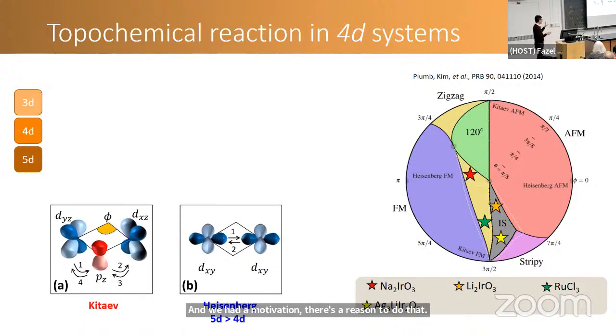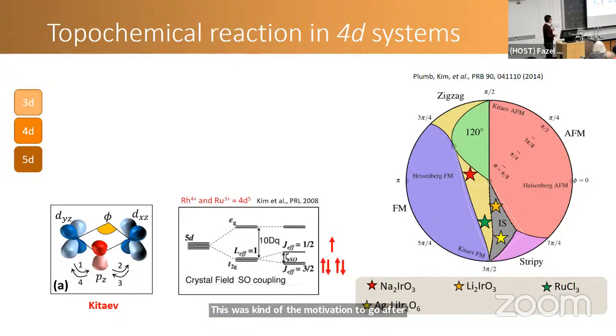And very simply put, that reason goes as follows. When you go from 5d to 4d, the spatial extension of d orbitals shrinks. 5d orbitals are bigger, 4d orbitals are smaller. And therefore, both this indirect Kitaev interaction and the direct Heisenberg interaction, both of them become weaker. But it so happens, if I understand correctly, that the Heisenberg interactions decay faster than the Kitaev interaction, which means that this ratio of Kitaev to Heisenberg coupling seems to be higher, in fact, in a 4d transition metal than in a 5d transition metal. This was kind of the motivation to go after 4d candidates of spin liquid physics.